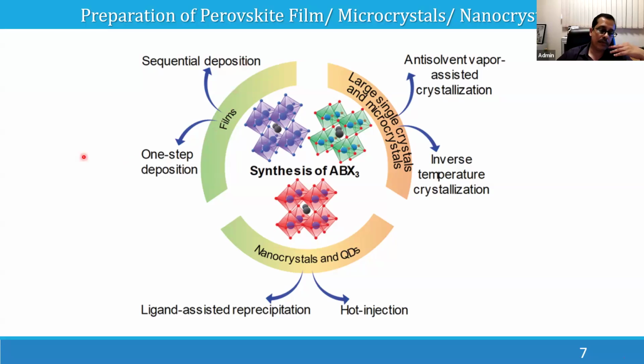The other one is the one-step deposition. You mix the ingredients like the lead iodide and the methyl ammonium iodide in solution in a conical flask, and you take that entire mixture and deposit it onto a surface. That is another method for making films.